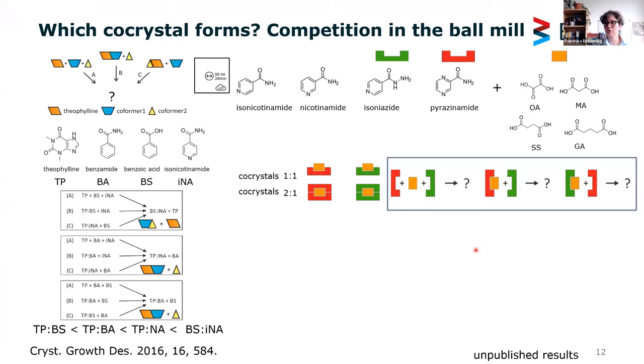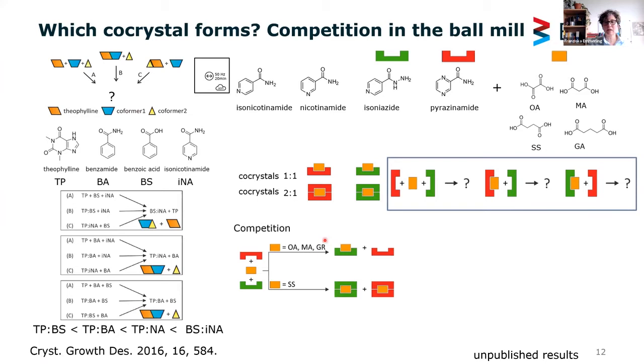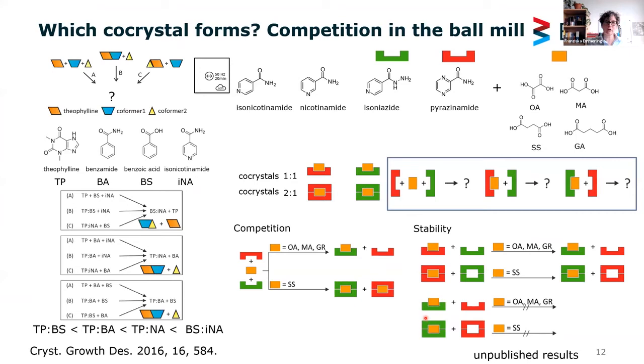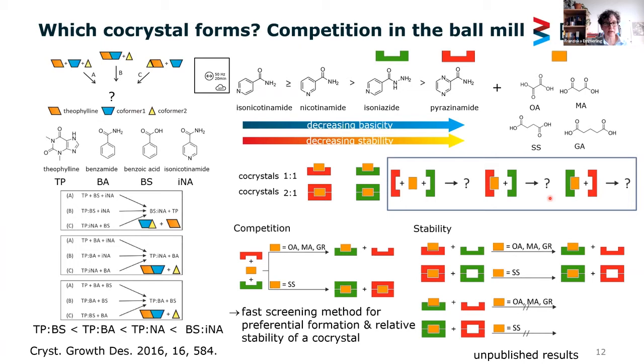And here you see what happened. So in these cases, we were able to form a co-crystal, but we would not be able to form a co-crystal with pyrazinamide and isoniazid. It would always win in these reactions. And it was also not possible to form the 2-to-1 compound. So in all cases, the combination of isoniazid and the co-formers is more stable. And that can be explained by a decrease in basicity. So it follows Etter's rules. And then we have here a decrease in the stability.